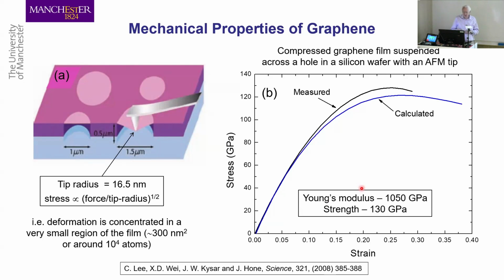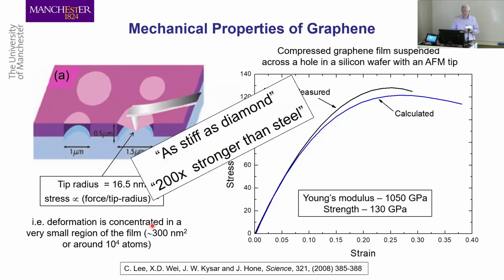And the interesting thing about this experiment is that the deformation is concentrated in a very small region of material, just under that tip. It works out about 10 to the 4 atoms. So here we are sort of doing mechanics on the atomic level. And I think the mechanics on the atomic level is quite different from that on the sort of bulk level, as we'll see. But anyway, this was the experiment, and it led to headlines such as, it's as stiff as diamond, 200 times stronger than steel. Well, a lot of people have used those sort of claims, and I think it's certainly as stiff as diamond, but certainly not 200 times stronger than steel, as we'll see.